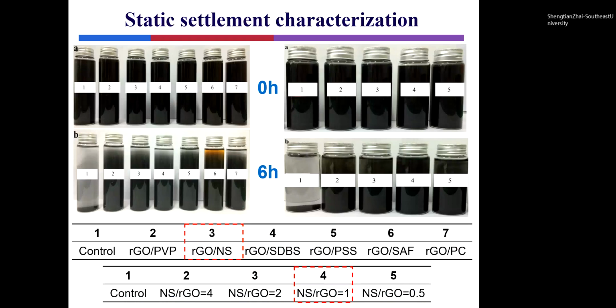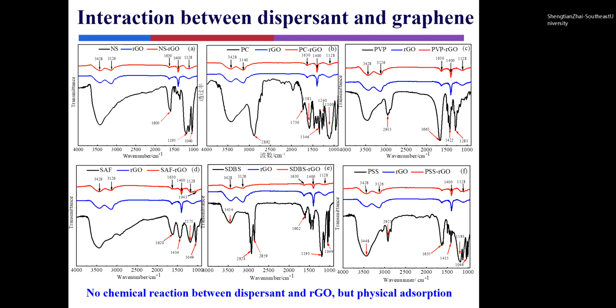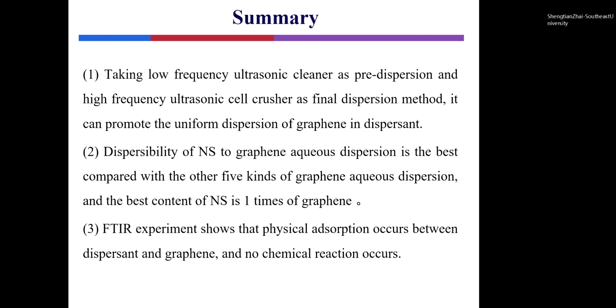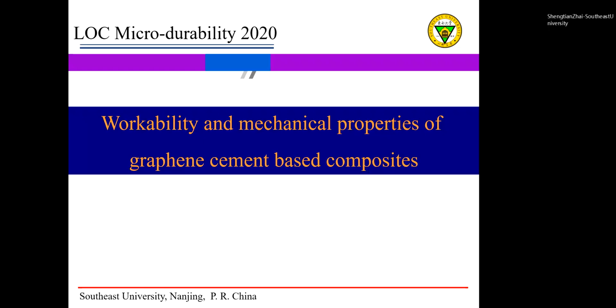This picture shows the state of the graphene dispersion with the different dispersants after static setting for 6 hours. We can see that the uniformity of the number 3 dispersion is the best. The picture shows the state of the NS graphene suspension with the different concentrations after static setting for 6 hours. This picture shows the FTIR analysis result of the dispersant, graphene and the suspension. From this picture, we can see that there's no chemical reaction between the graphene and the dispersant, just physical adsorption. According to the experimental result, the summary is as follows. Next, please look at part 4.